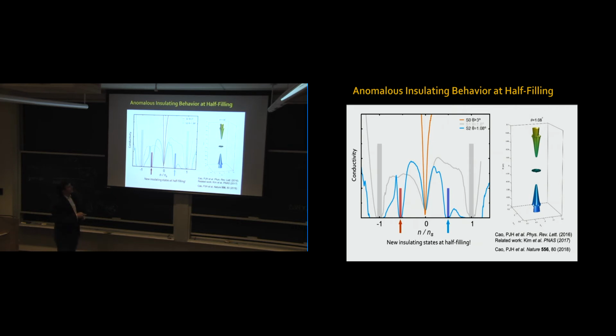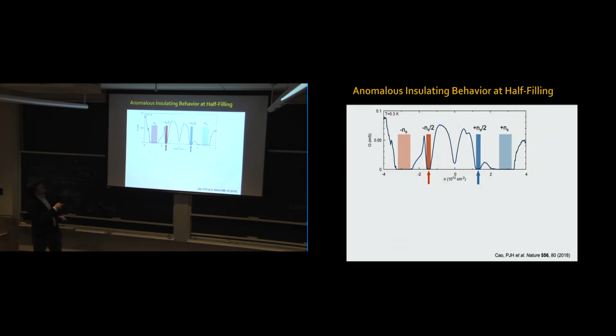So let me show you now, these are real axes, in units of millisiemens for the conductance, and density of electrons in units of 10 to the 12 per square centimeter. This is a 2D material. Just to remind you, from charge neutrality in this direction we're adding electrons to our system, and towards the left we're adding holes. So when we saw this insulating behavior at half filling, we realized it was very unusual.